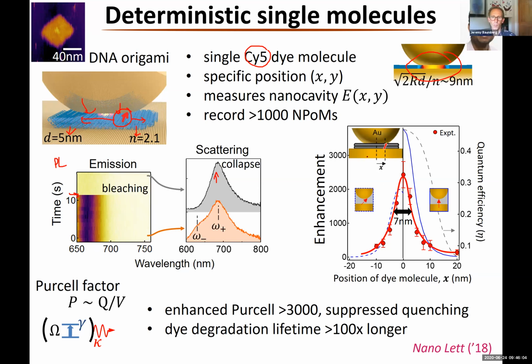Okay. So what we do in this system here now is that for a particular sample, we use a DNA origami where we can trap the molecule in a particular position, which is X away from the center of the gap there. And then we'll look at 1,000 or so nanoparticles on mirror. We've automated everything and just look at the enhancement of the light. So this is basically the enhancement we see of the light for when the dye molecule's in the center, and these are for different distances away.